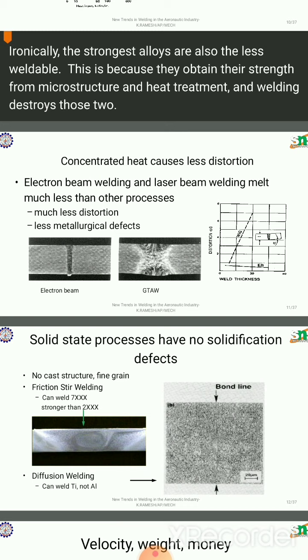Concentrated heat causes less distortion. Electron beam welding and laser beam welding melt much less than other processes, so much less porosity and fewer metallurgical defects, compared with gas tungsten arc welding. The solid state process has no solidification defects, no cast structure, and fine grain.